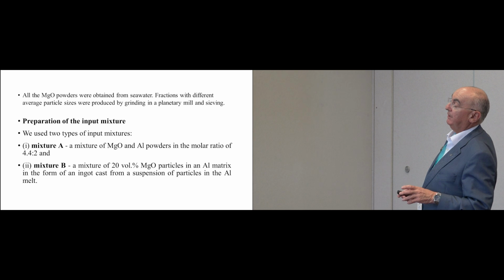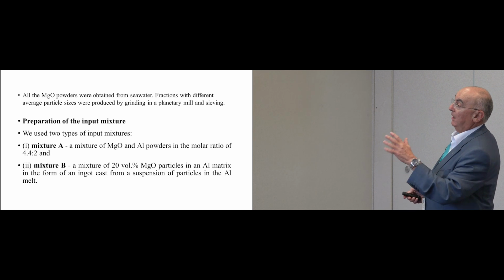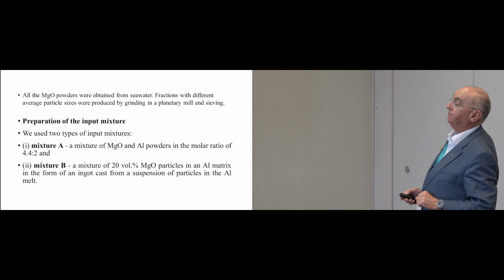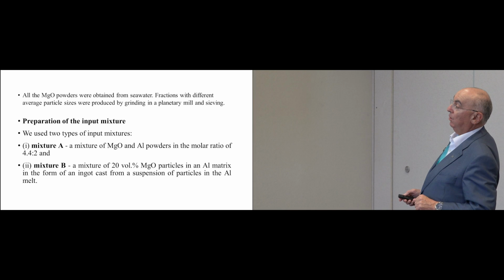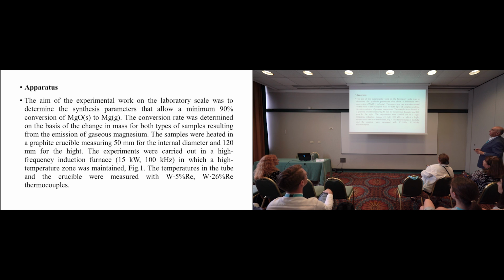So, okay, we prepared two mixtures, one of magnesium oxide and aluminum powder, and another one of 20 volume % of magnesium oxide particles in aluminum matrix in the form of ingots cast from a suspension of particles in aluminum melt. You will see later on. So, of course, we use this induction furnace in argon flow atmosphere. And here you will see also what we try to make in a pilot scale.